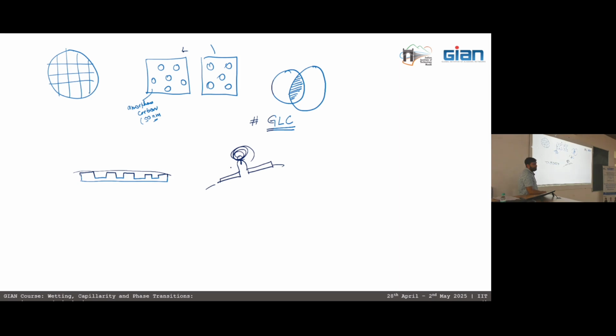These gas ones are pretty stable. So gas ones you can observe for a very long time, 2-3 hours they'll be there. And when you adjust the electron beam, you can basically control the saturation level there. If you make the beam more intense, bubbles will grow. If you make the beam weaker, the bubbles may shrink. That all you can observe there.